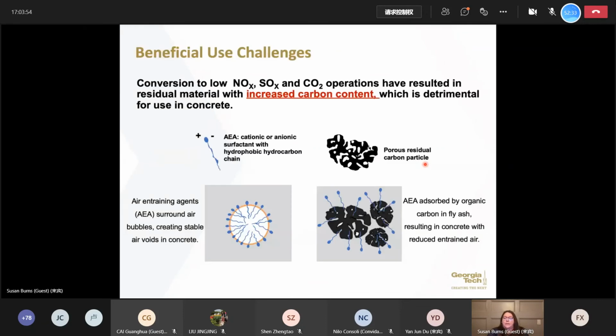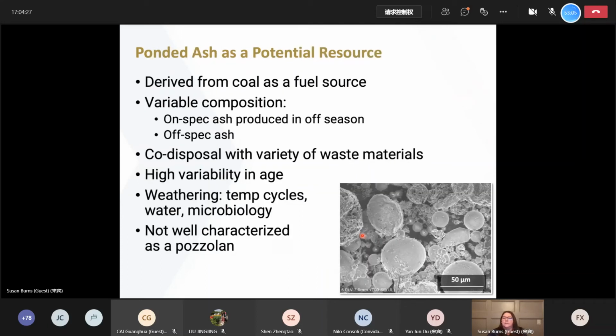As I mentioned before, the organic carbon is a serious problem for us in terms of concrete production due to the sorption of the surfactants of our air entraining agents, right? So we know here in this case that we want to make air bubbles uniformly distributed throughout our concrete for the beneficial uses that we have there. What happens, though, is these organic phases will sorb our surfactants, and that's going to cause us a problem. So in some cases, when we've got these really high organic carbon content fly ashes, we want to look at alternative uses for them.